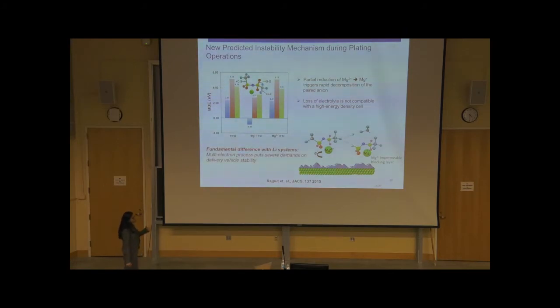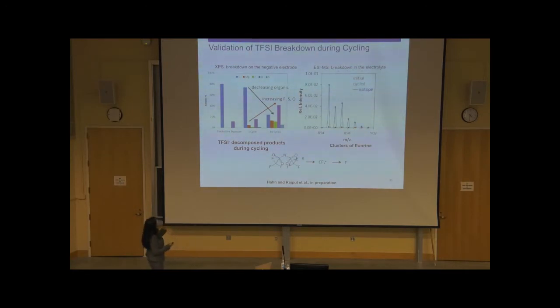So the fundamental difference between lithium electrolyte and magnesium electrolyte is that this multi-electron process puts a severe penalty on the stability of the salt anions. Our experimental collaborators at Sandia National Lab were able to validate such TFSI breakdown, where they found TFSI-derived products on the electrode surface when they cycled the battery. So it's likely that TFSI breaks down during the cycling process. They also found some fluorine clusters in the electrolyte, which confirms that TFSI breaks down through this carbon-sulfur bond, which liberates fluorine. So these results might not be very encouraging for someone to pursue magnesium batteries.